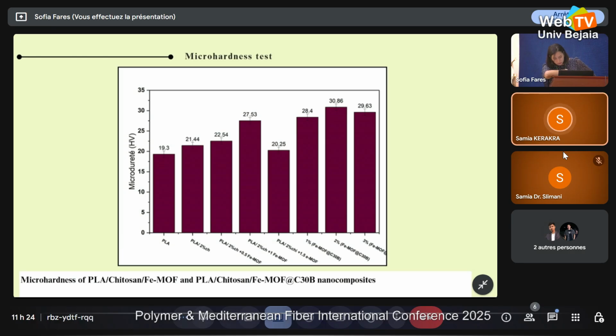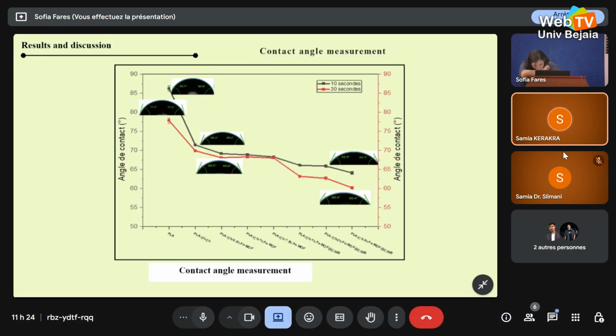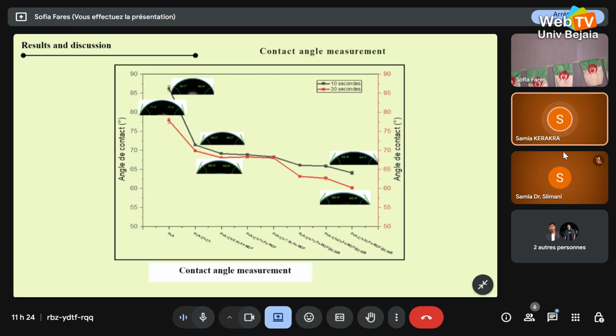Contact angle measurements. The change in contact angle of the films at 10 seconds and 30 seconds. And the results for PLA composites modified with 2% chitosan and incorporated fillers too show significant change in surface wettability. The addition of chitosan reduced the contact angle, increasing hydrophilicity, and adding both fillers or the composite further reduces the contact angle, making the surface more hydrophilic.